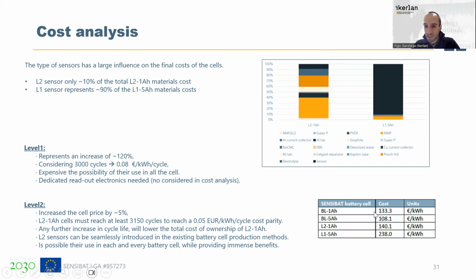And you can see here we did some projections at industrial scale, and we estimate a cost of around 100 euros per kilowatt hour for 5 ampere hour baseline cells, and 30% more for smaller cells. If we add the L2 sensor, we have an increase of less than 10% of the price for 1 ampere hour cells. But in the case of the L1 sensor, we have more than double the euros per kilowatt hour price. So in summary, the L1 sensor represents an increase of more than 120% over a baseline cell without any sensor.